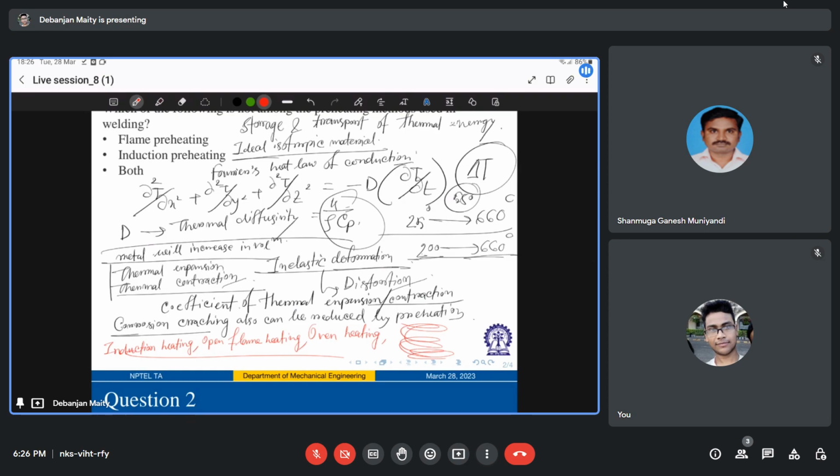So what are the pros and cons of induction heating? In terms of advantages, induction heating offers a quick setup, often in less than 5 minutes maybe, and a fast rise of temperature. It also produces a uniform heating area, making it easy to achieve and stay within a strict temperature window, right?